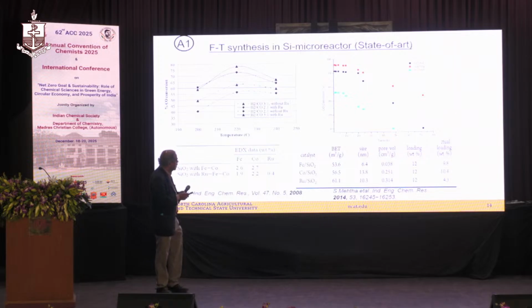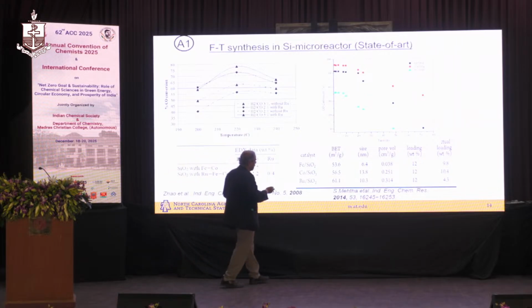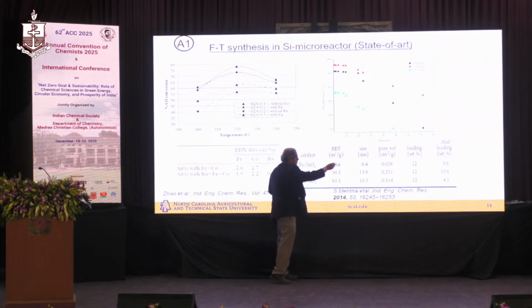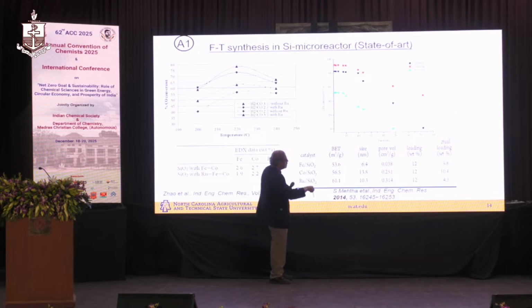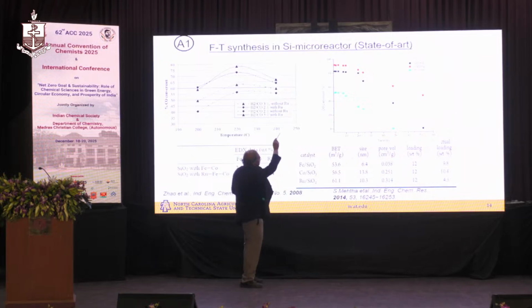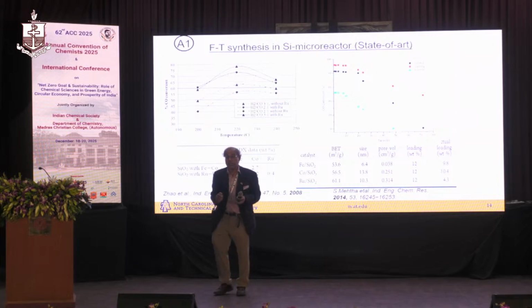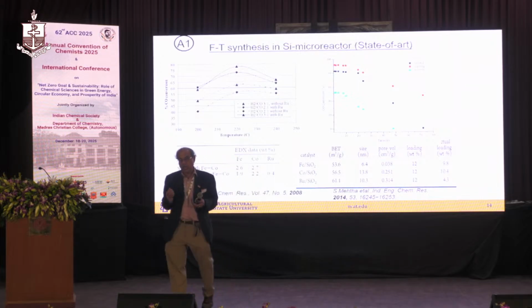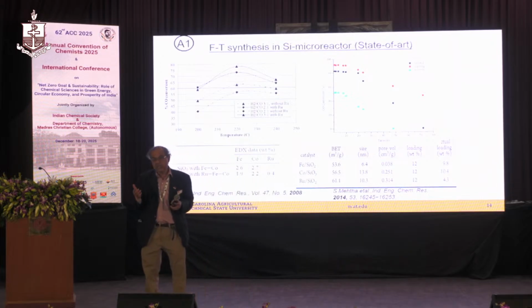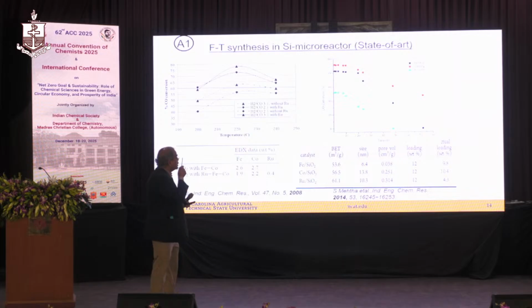And then these are the typical BET surface areas and the pore volumes, and you can see the weight percent. We tried to maintain the intended loading, and then we looked at the stability of the catalyst. Why stability of the catalyst? Because if you're running your process, you need to make sure your catalyst is very stable. Otherwise, it's no good and you cannot really apply it. So that's why you do the stability studies.